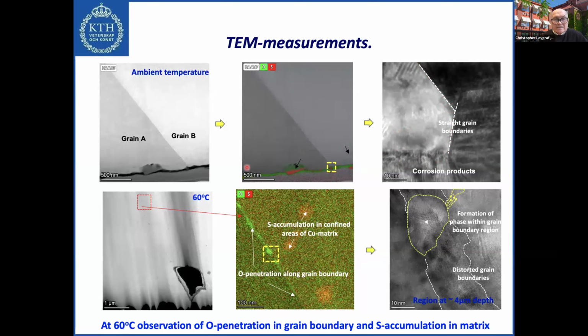But if you take the results at 60 degrees, and here we select an area where we know that the grain boundary is. This is an area which is some few micrometers inside, away from the corrosion products. And we magnify it. Here is now the elemental distribution. And you can see clearly, the green is oxygen, the red is sulfur, that oxygen has penetrated along the grain boundaries quite far inside the material, about 4 micrometers inside. It can go further, it is just a selected area.